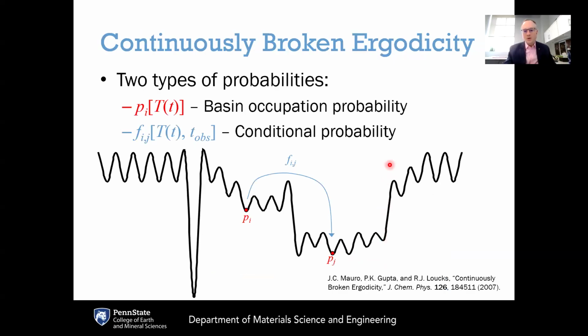So we published back in 2007 a generalized form of Palmer's approach of broken ergodicity that addresses all of these issues. It's called Continuously Broken Ergodicity. This was published in the Journal of Chemical Physics in 2007. And this is based on two types of probabilities that are defined. If you have any arbitrary energy landscape as shown here, it doesn't matter if you can define components or not. Continuously broken ergodicity is not based on defining components. It doesn't use any assumptions of internal ergodicity or confinement.